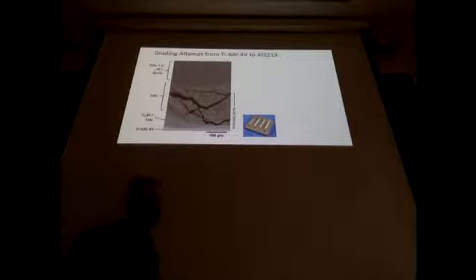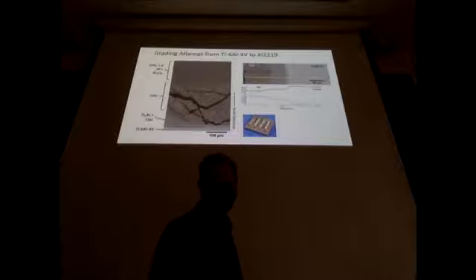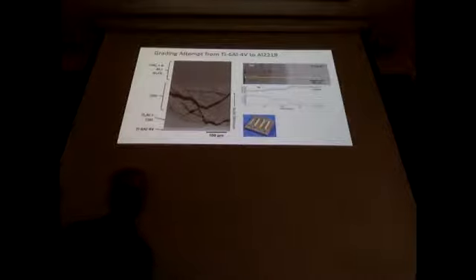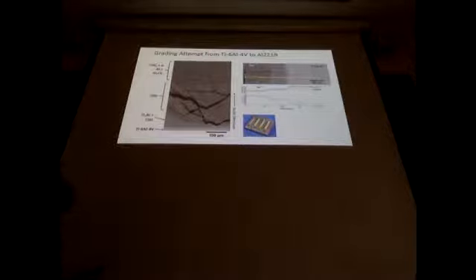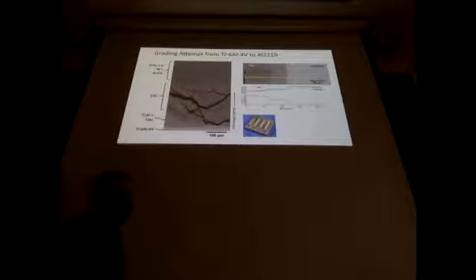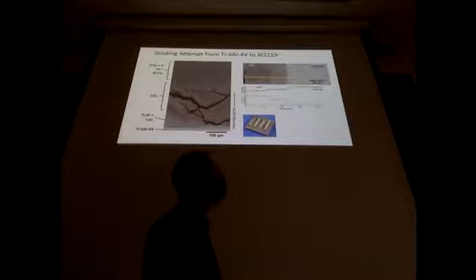This is something we immediately saw, so what can we do? The issue is those cracks extend basically right to the Ti-64. This is the Ti-64 base plate, and the minute we start adding aluminum, you can see the cracks start coming in. So even though we're fine here, it seems that grading with an aluminum alloy on titanium is probably a no-go, as far as we can find out.